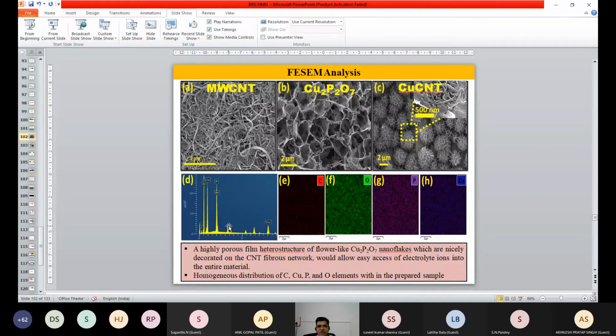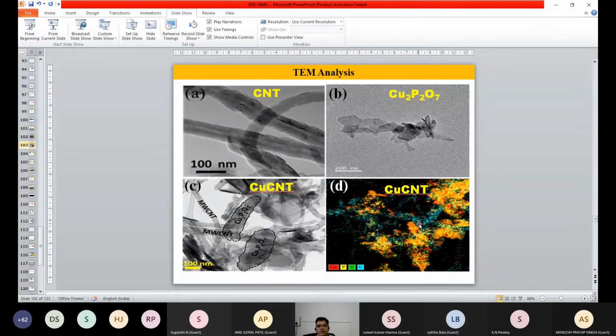So we have checked this in the EDX mapping, right? And we have done certain elemental analysis, so that you can see the carbon, oxygen, P and Cu, and the homogeneous distribution of the material in terms of P, O and Cu on the carbon nanotube. So here you can see that this is a carbon nanotube coated with copper phosphate, Cu2P2O7 on the carbon nanotube, and this is the elemental mapping. So there is a uniform distribution of the elements on the carbon nanotube, and that is required for the supercapacitor application with very high surface area.